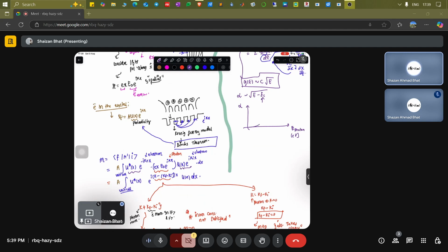You get an absorption like this, where this is basically some EC, conduction band energy. This basically says that all of the photon energies below this conduction band energy are not going to be absorbed, and all of those energies which are above this particular conduction band energy are going to be absorbed, and they increase, sorry, they increase in a square root fashion.